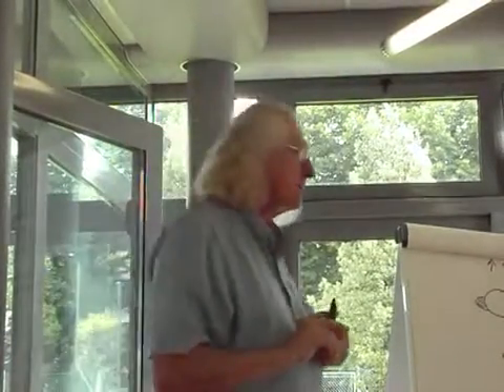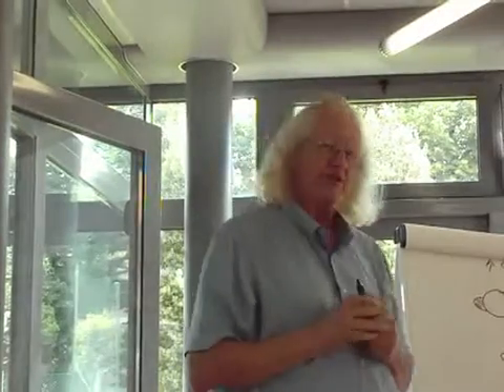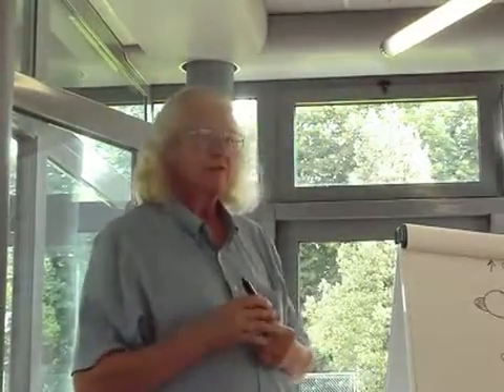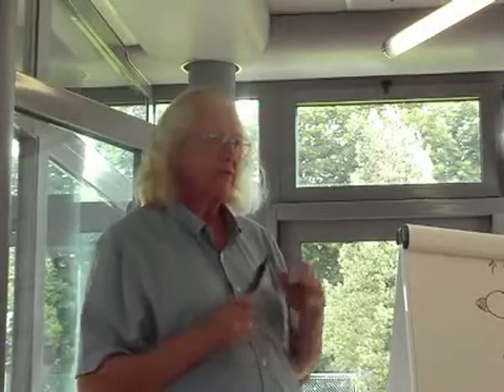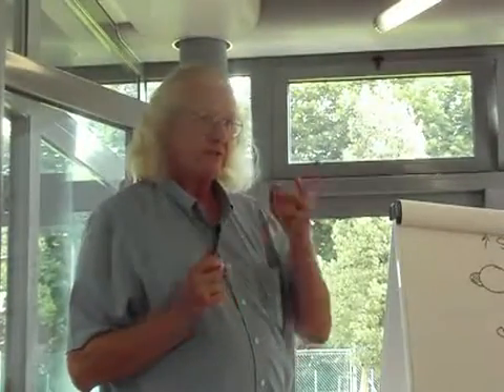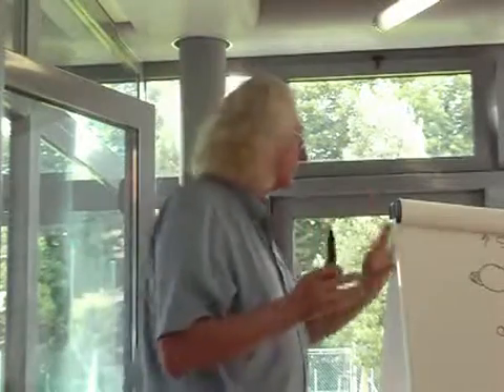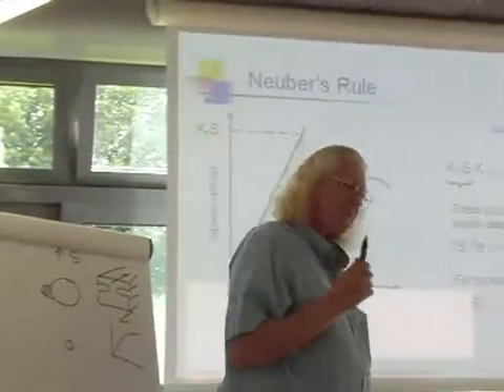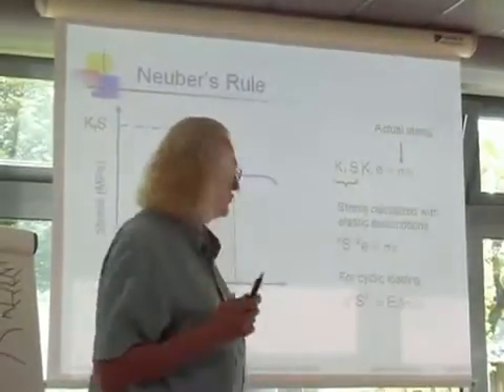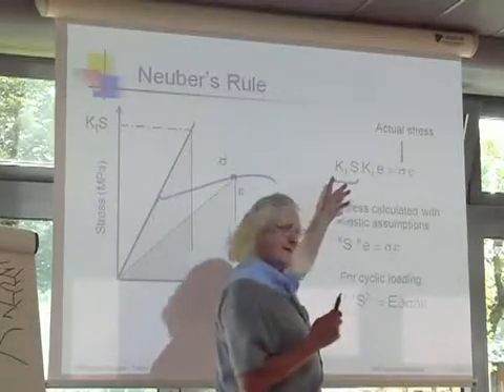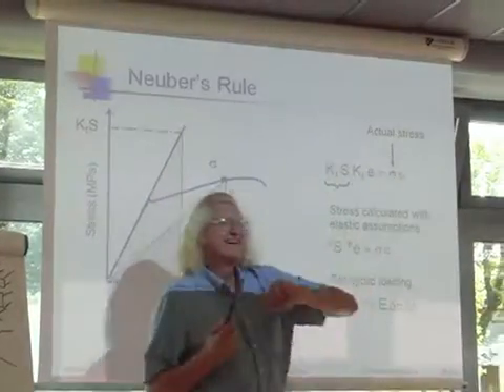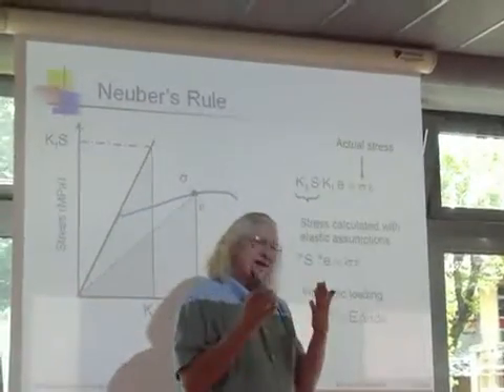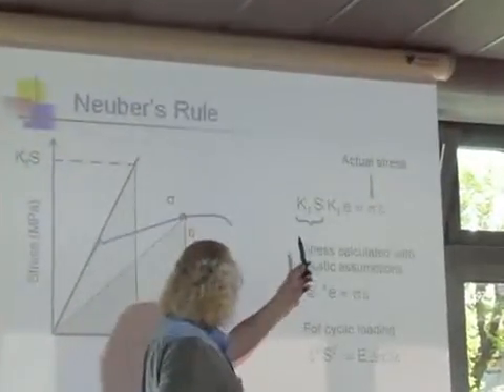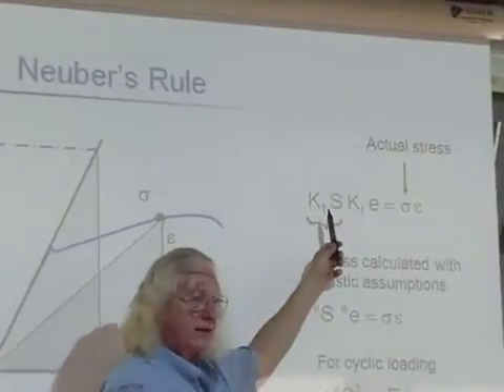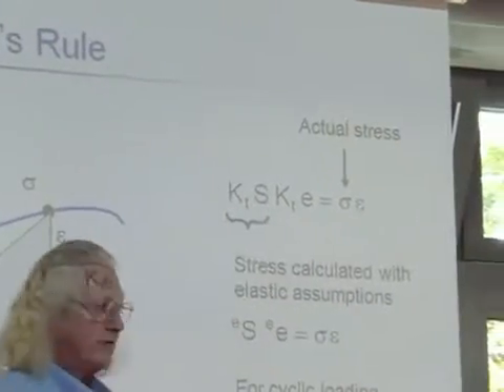And he wrote down that the real stress concentration factor is equal to the geometric average of the stress and strain concentration factor. And that's what he wrote. Right? I've simplified those 7 or 8 pages of mathematics into this one formula up here. What it said really was, if you look at the elastic solution for stress and strain, and I wrote this as kT times the nominal stress